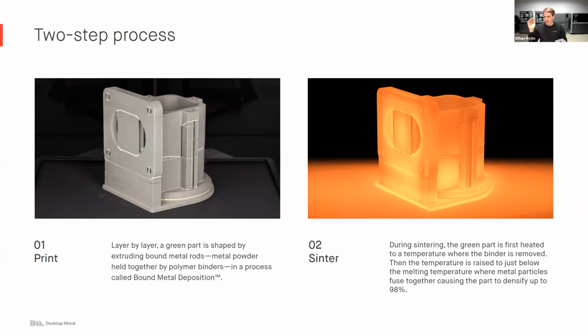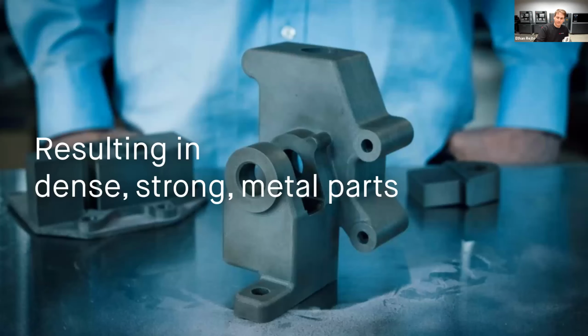But from here, we go into the furnace. The first step in the furnace is to remove that binder material. We're going to get to a temperature where that binder is able to be evaporated, and then what's left behind is that metal powder. We get just below the melting temperature of the material, and our particles actually fuse together, causing the parts to densify up to 98%. The part does shrink about 15% during this process, but of course, that's fully controlled by our software to ensure you're getting the desired dimensions that you require. So you can see, we have our green part that's coming off the printer and our final sintered part here. That's the metal we want. So the result of the furnace is what we're seeing, these strong, dense metal parts. And you can hear, this is now a strong, dense metal part ready for those end use applications, ready to be put into the field.